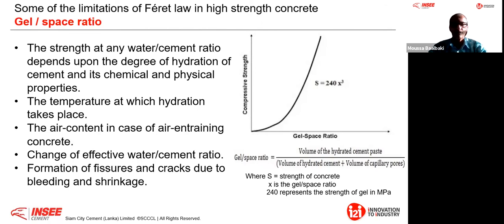not only to water. And now you will see that this ratio becomes very important, because the more hydrated product we produce, the less capillarity pore we have. Therefore, this ratio will increase. By increasing the ratio, we increase the compressive strength. That is really important. That is fundamental.